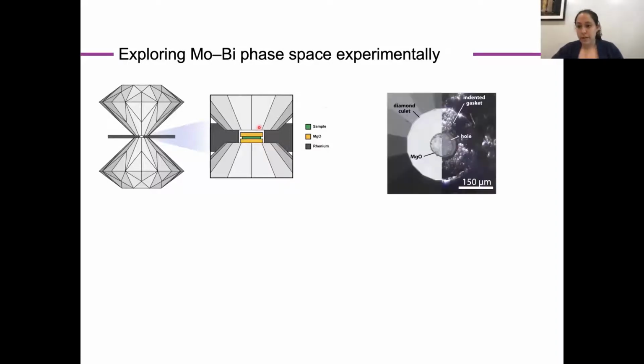Here's a picture of what that ends up looking like. You can think of it as this being, say, the top diamond in our setup, where we put one laser cut MgO disc, and here's the bottom diamond in our setup, which has a rhenium gasket, which ensures that our samples stay confined, another piece of MgO. And we're going to place a thin foil of molybdenum bismuth onto one of these discs, and then close up the diamonds to create that sandwich.